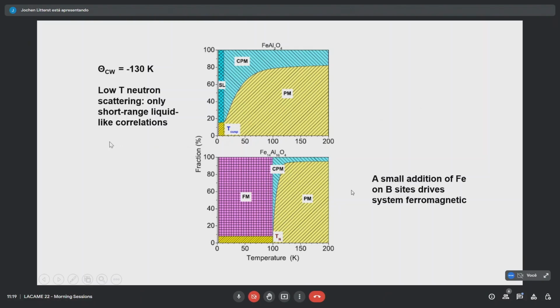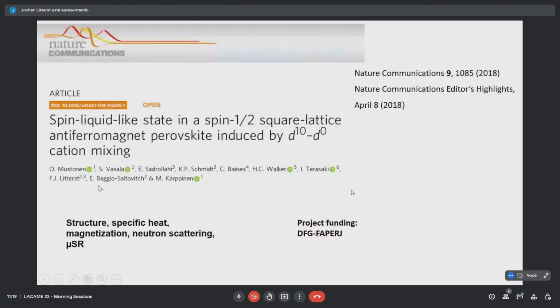Notably, if you disturb this system with a little bit of iron that is sitting on B sites, that's happening here. You have added more irons that can go not only to the tetrahedral, but also to the octahedral sites, only a few percent, you immediately switch over to a ferromagnetic state. So it's very, very sensitive. So the spin liquid state is a very delicate phase. And as we had seen before, also with this tantalum compound, it depends crucially how well defined are the proportions sitting on different lattice sites.